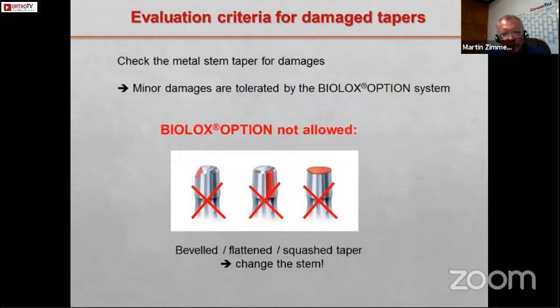But there is some limitation. The sleeve system has some limitation, as you can see in these three schematic pictures of the deformation that you can have on the taper of the stem. If you imagine that you put the sleeve on the taper of the stem and you have a waggling, and you feel the impression is not stable, then you also recommend not to use this system and most probably to change the stem. But if it's too difficult to really change the stem, then use a ball head in metal.